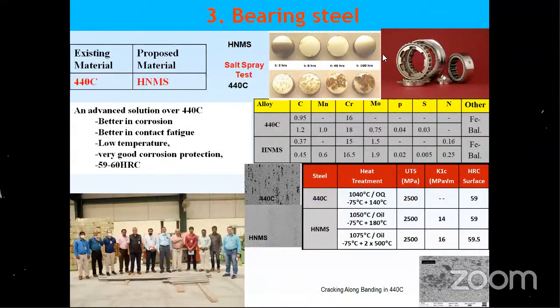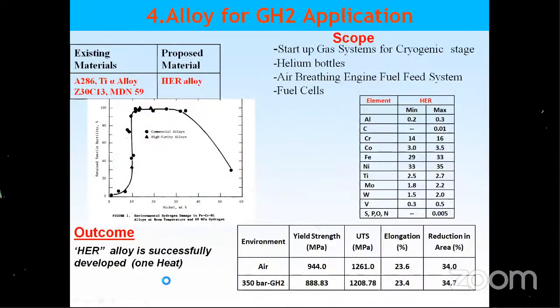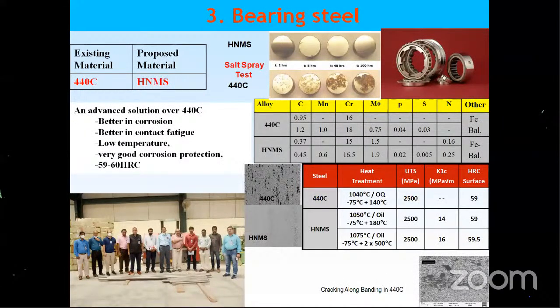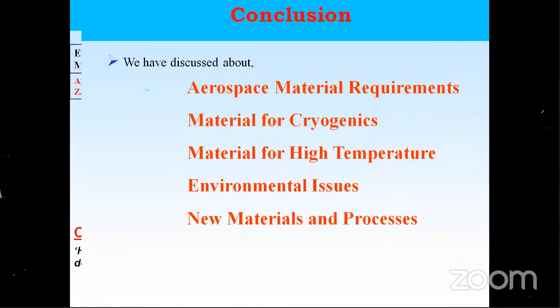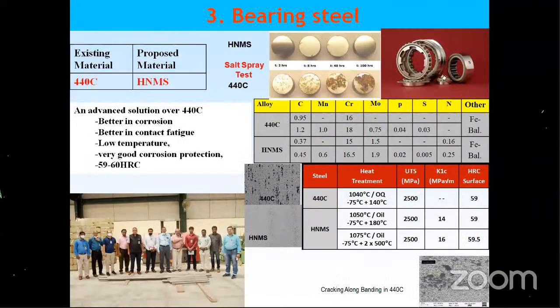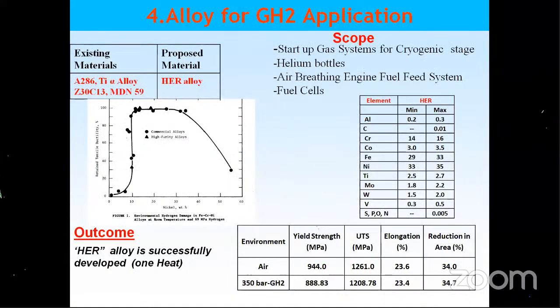So corrosion resistance is superior, and I have already made this material and supplied the rods to our team in IISU, Inertial Systems Unit, for making bearings. It has two levels of strengthening. I can do normal tempering at 140 to 180 degrees centigrade, as well as secondary tempering at 500 degrees centigrade. The advantage of secondary tempering is that it offers higher toughness compared to primary tempering, while giving similar hardness. So you have two options. This material has also been developed and given to my IISU team.